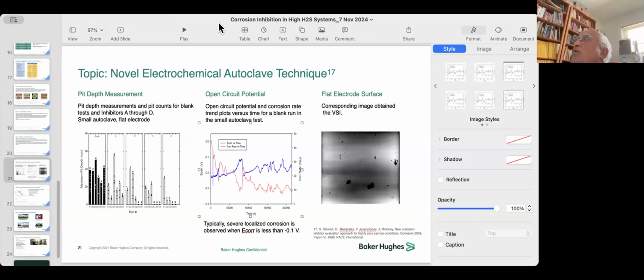If it's working at very low concentrations, I propose something known as the self-assembled monolayer theory of corrosion inhibition for imidazolines, which are one of the important ones. It binds to the surface, or to the oxide layer on the surface. The binding can be such that they form a self-assembled monolayer. The oxide structure is structured, so the binding will also be structured, and then you have a hydrophobic tail that prevents corrosion. Now, this is true for oleic imidazoline. For others, it may be different.